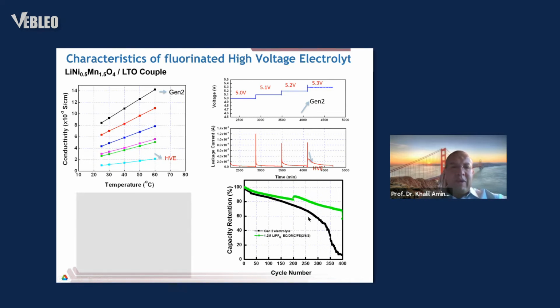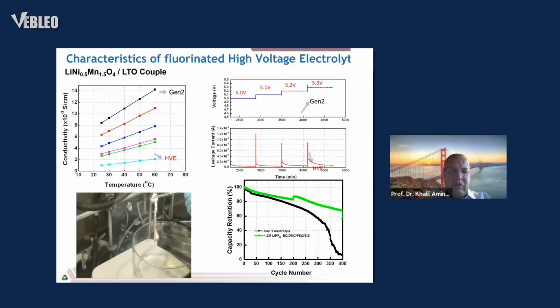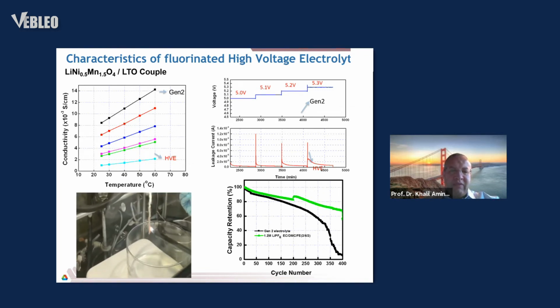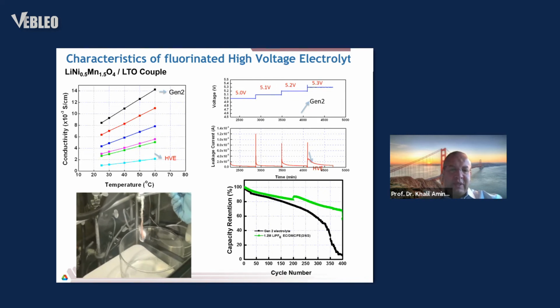We also look at the flammability of this material using a flame test. For instance, we take a glass wick, fill it with the electrolyte, and hit it with the burner and see what happens. So we start first with the fluorinated electrolyte. As you can see, once you hit it with the flame, it doesn't catch flame, as you can see here.